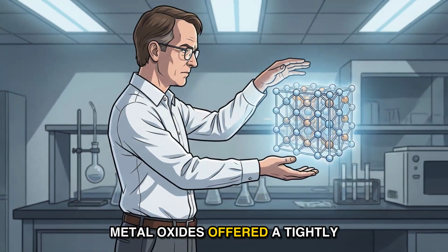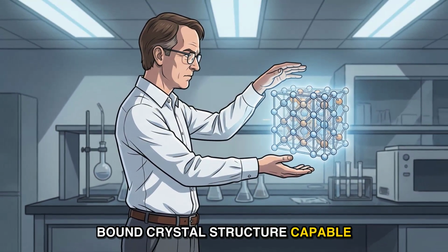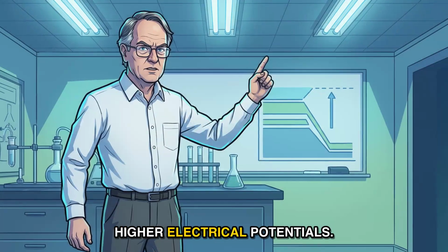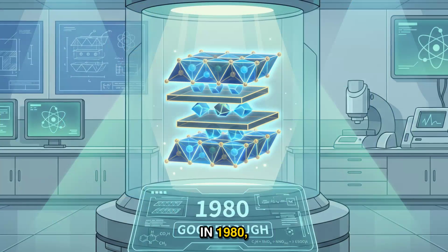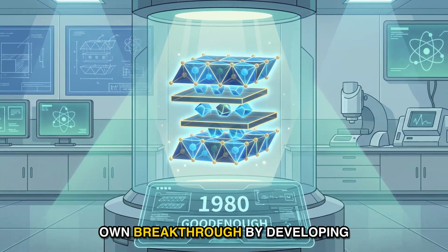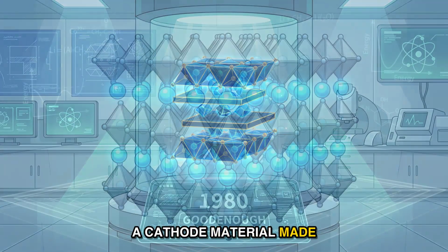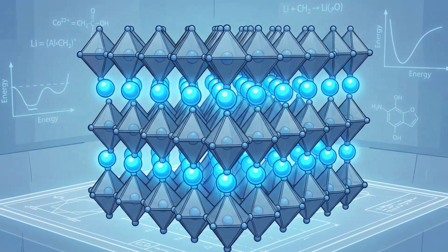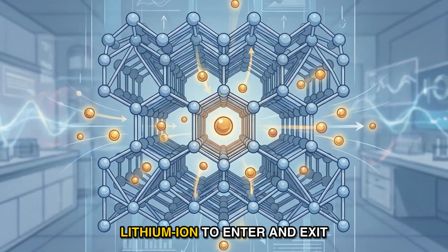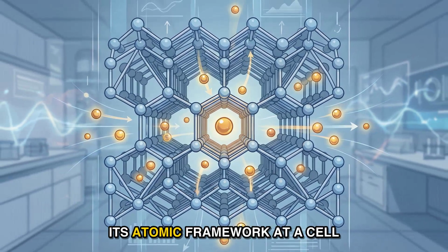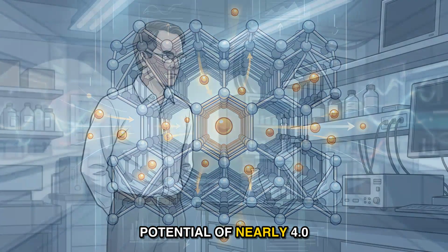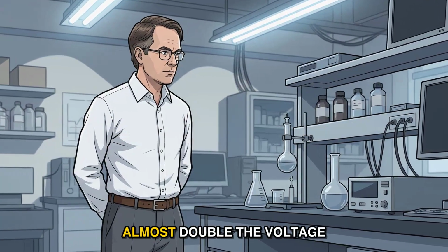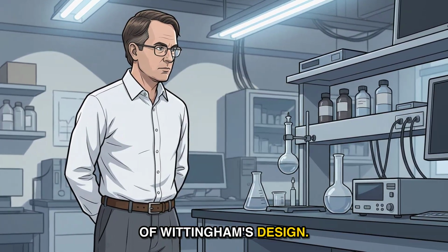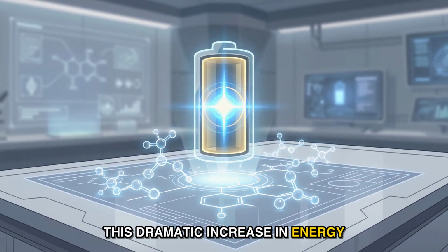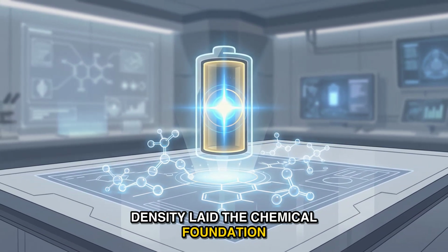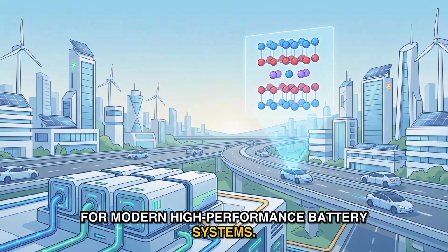Metal oxides offered a tightly bound crystal structure capable of operating at significantly higher electrical potentials. In 1980, Goodenough achieved his own breakthrough by developing a cathode material made of lithium cobalt oxide. This new compound allowed lithium ions to enter and exit its atomic framework at a cell potential of nearly 4.0 volts, almost double the voltage of Whittingham's design. This dramatic increase in energy density laid the chemical foundation for modern high-performance battery systems.